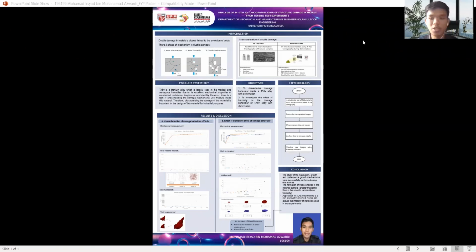Right. So as for the introduction, this project focuses on ductile damage in metals. Ductile damage is closely related to the evolution of the voids, and there are three phase mechanisms in ductile damage. First is void nucleation, which is the formation of small cavities at the cross section. Second is void growth, where the voids grow with plastic deformation, and the last one is void coalescence, where the voids merge to form micro cracks, and the crack continues until fracture.